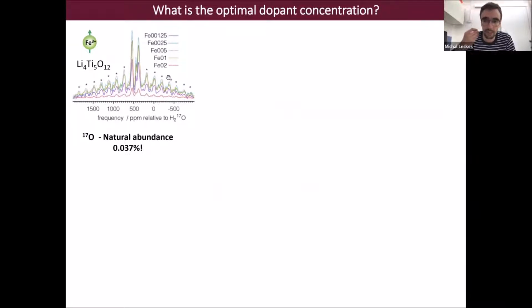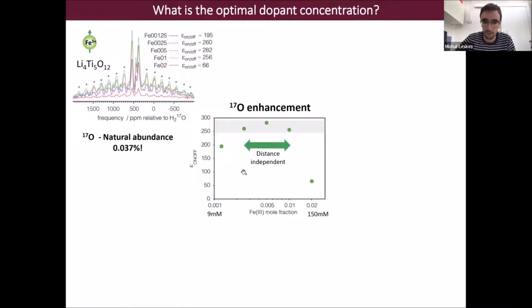Based on what I just told you in the previous slide, the concentration does not affect the DNP enhancement, since the enhancement is independent of the distance. And that's exactly what we observed. Here is the enhancement of the oxygen-17 versus the concentration of iron. We see that over a very large range of concentration, almost an order of magnitude of mole fraction of iron 3, the DNP enhancement stays more or less constant. This is just because the enhancement is independent of the distance.